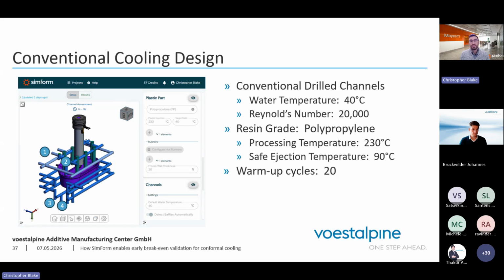We set up the detailed cooling simulations again in SimForm. Now this involved assigning materials to the inserts, the mold base, the ejector pins, and the components of the hot runner hot tip. As was mentioned earlier, the resin material is polypropylene. For the medical tray, we use the processing temperature and safe ejection temperatures that are noted here on the screen. On the left, you can see the 4-channel network of the conventional cooling design with the inlets identified 1, 2, 3, and 4. The water from the chiller was set to 40 degrees Celsius, and based on the preceding CFD analyses of the water flow in the channels, a suitable flow rate was applied to achieve a Reynolds number